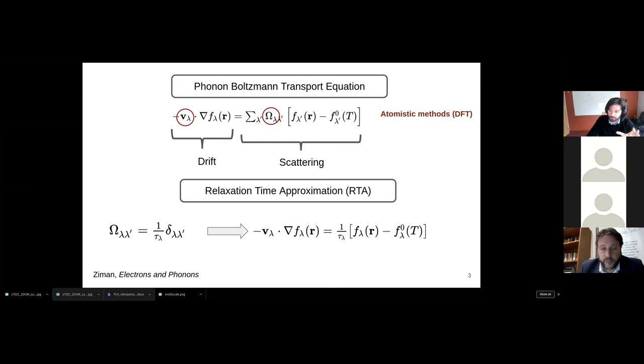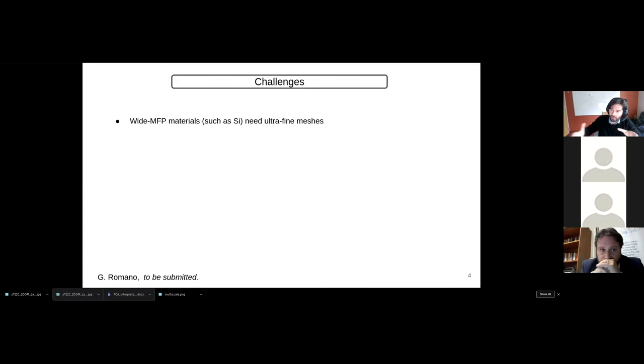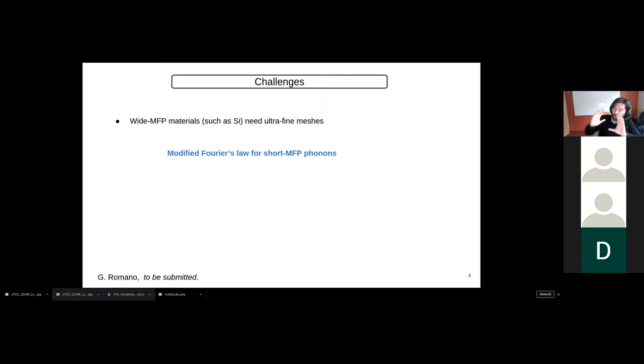This is a little complicated because we have to solve this equation. In our case, we solve it deterministically, and there are two main challenges. The first challenge is that in wide-MFP materials we need an ultra-fine mesh, whose complexity is as large as the number of elements of our mesh. We fix this problem by identifying a modified Fourier's law that can be employed for short mean free path phonons. Here we identify three regions for phonons: diffusive phonons, ballistic phonons, and quasi-ballistic phonons. Those three regions are computed differently.